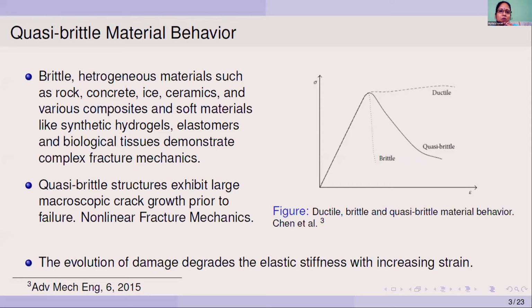These structures do not follow linear elastic fracture mechanics, and hence nonlinear fracture mechanics is needed to study their fracture behavior. These quasi-brittle materials undergo moderate hardening prior to the attainment of ultimate tensile strength and are characterized by post-peak softening with a rounded peak as shown in this figure. This strain softening is basically the degradation in material stiffness with increasing strain and is observed at a continuum level in damaged quasi-brittle materials.